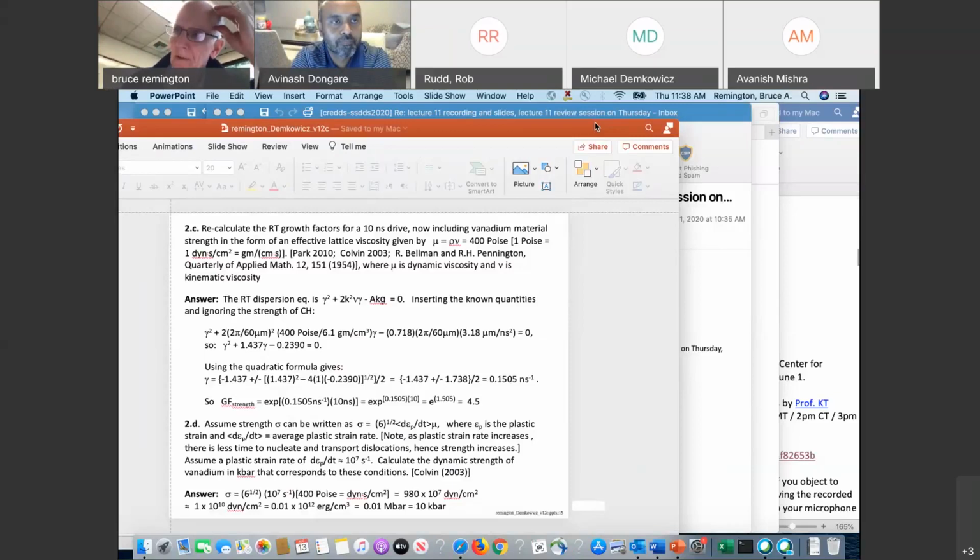Yeah, it does. I mean, the question is, as you vary the temperature, if you keep the material solid, so there's a lattice, you can vary anywhere from a factor of 10 below the melt temperature up to, say, 90% of the melt temperature. And the effects can be large. In particular, the deformation mechanism can change as a function of temperature, and you can move from thermal activation into phonon drag and back. And so we do vary the temperature intentionally as we're doing our experiments.